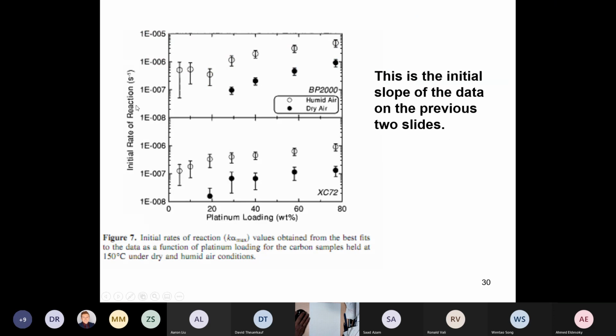So what you're seeing here is that the initial rate of reaction in the dry case is about an order of magnitude lower than for the humid case. And two different carbon supports were being studied here. XC72 is a fairly low surface area carbon black, maybe 250 meters squared per gram. And Black Pearls 2000 has 2,000 meters squared per gram.